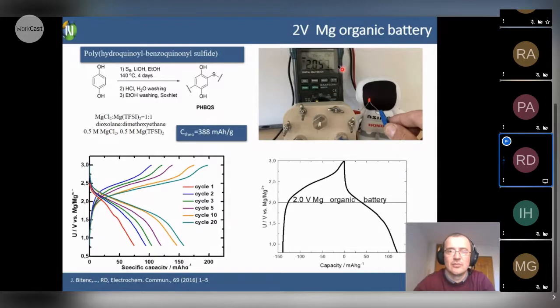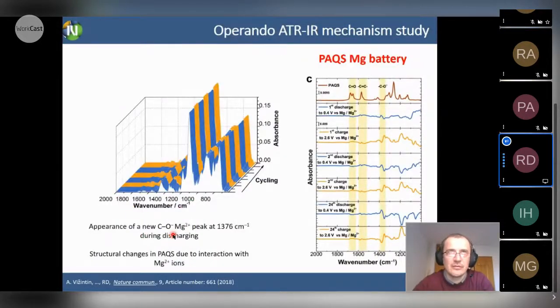And you can see here the battery has 2 volt, and everything is shown here, and it was published almost 5 years ago. So basically, using some benzoquinones we can obtain a battery which has 2 volt and which can run several cycles, and you will see later also several thousand cycles. But the question from the beginning was, what is the mechanism? What is the driving force for these charge transfer reactions? And do we really have interactions between quinone molecules and counter anions, counter cations, or do we have a different mechanism?